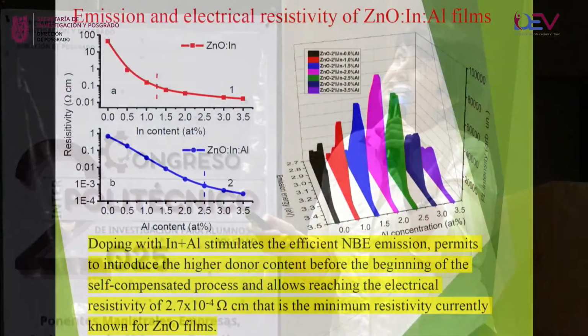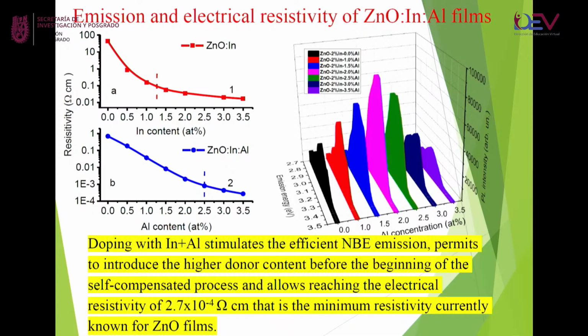And you could see here the electrical characteristics. When only indium was used, the resistivity was 10^-2, this is 0.01 ohm centimeter. Resistivity units, ohm centimeter. But when we use two elements, indium and aluminium, our resistivity was 10^-4 ohm centimeter. This is two orders of magnitude higher conductivity of the film in comparison with doping with one element. And this conductivity that I present here is a world record result for zinc oxide.